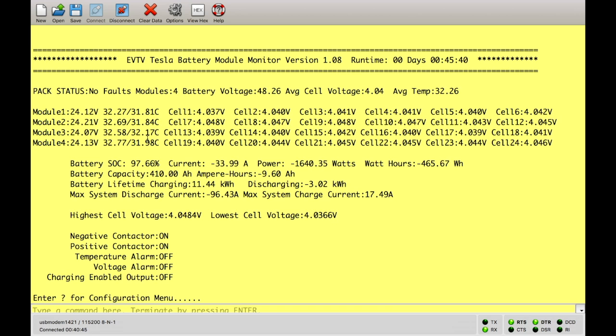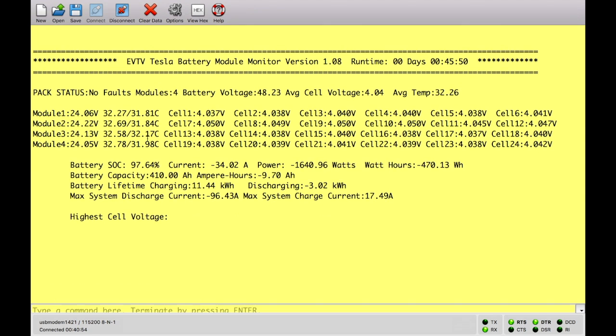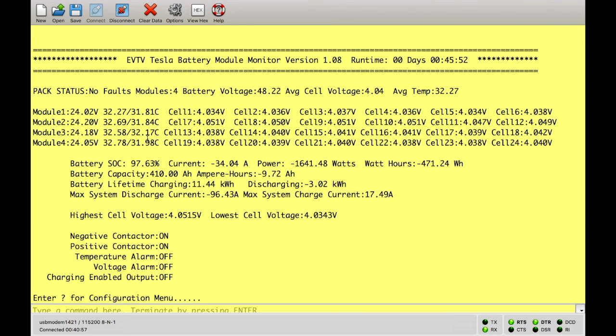But that can build up over hours. And so if you put on your pack and 10 hours later it trips and goes offline, and you fire it back up and it works fine, and 10 hours later it kicks out, it's easy enough to hook up a laptop and watch those temperatures climb over time, and you may decide that additional cooling is probably required. Stay with us.